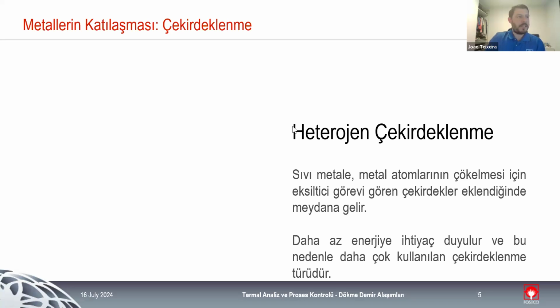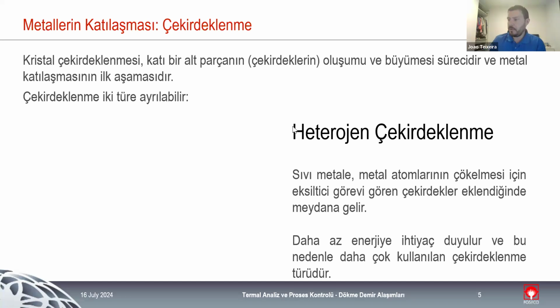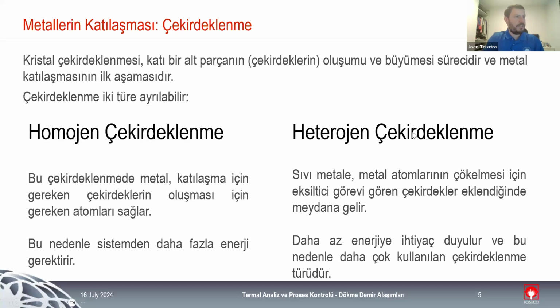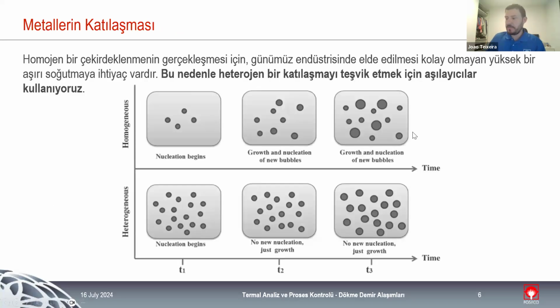The other type of nucleation is called homogeneous nucleation, and this one is achieved when we don't have any type of inoculation. So when you don't give anything for the stable nuclei to grow to the liquid metal, and we just give time for the solidification to happen, this type of nucleation takes a long time. Normally, we don't like this because, as mentioned, it takes longer, and we have a lot of problems associated with this, especially with the presence of carbides.